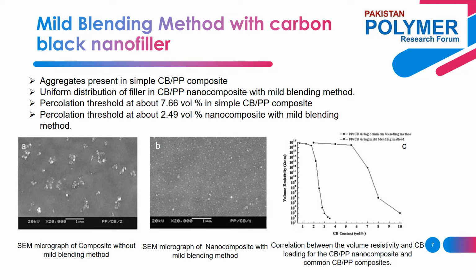The correlation between volume resistivity and carbon black loading for the carbon black and PP nanocomposite and the common carbon black and PP composite is shown in figure C. The carbon black and PP nanocomposite prepared using the mild blending method was found to percolate at a threshold of about 2.49 volume percentage of carbon black, whereas the common carbon black and polypropylene composite had a percolation threshold of about 7.66 volume percentage.